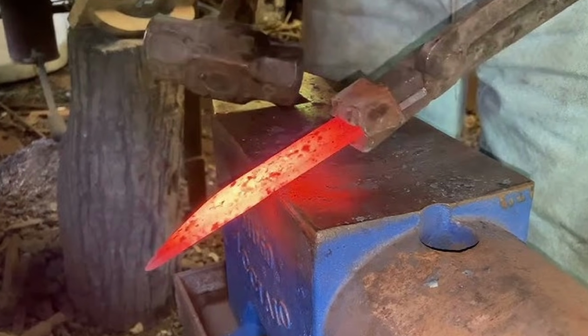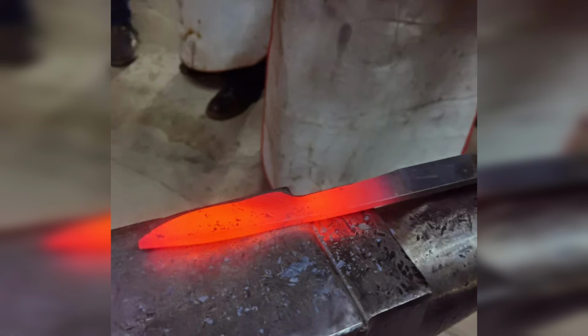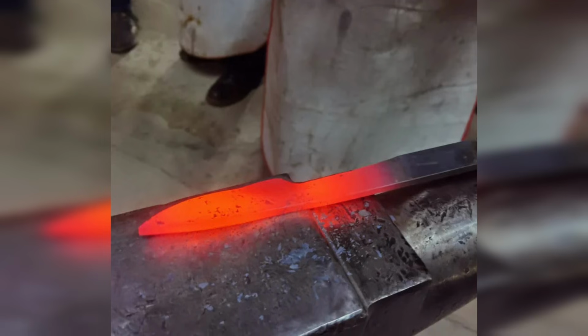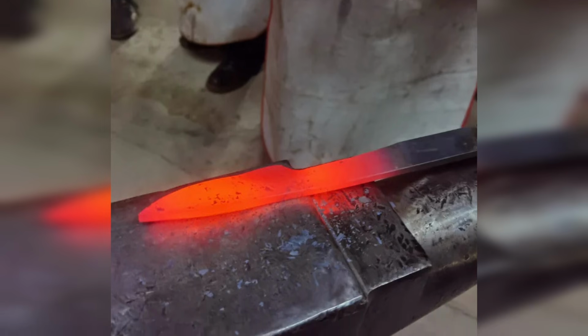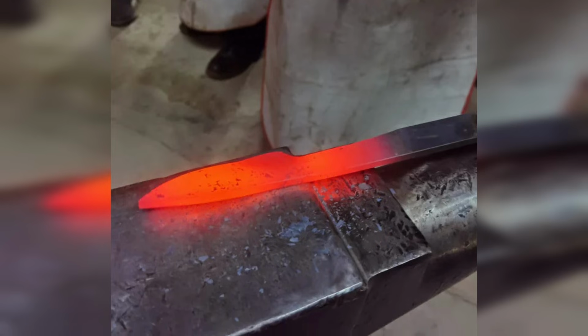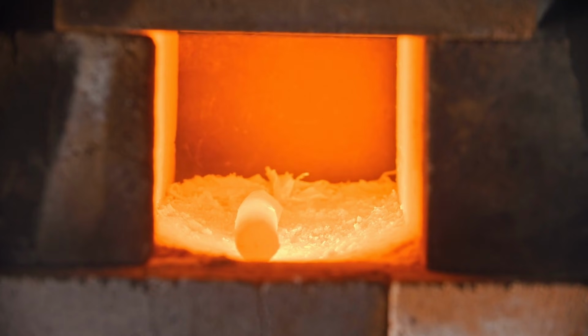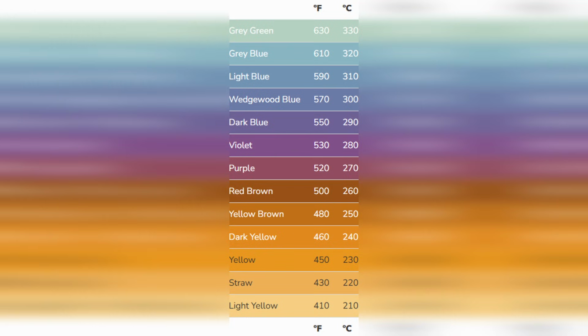Pale straw yellow, deep bronze, peacock blue, purple. These colors were not decoration, but an exquisitely precise temperature gauge caused by oxide layer thickness forming on the steel surface. Each color corresponded to a specific temperature, and each temperature produced different material properties. Straw yellow around 230 degrees Celsius made steel perfect for cutting edges. Bronze around 255 degrees was ideal for springs and swords needing flexibility. Blue around 300 degrees created tools that could absorb impacts without shattering.